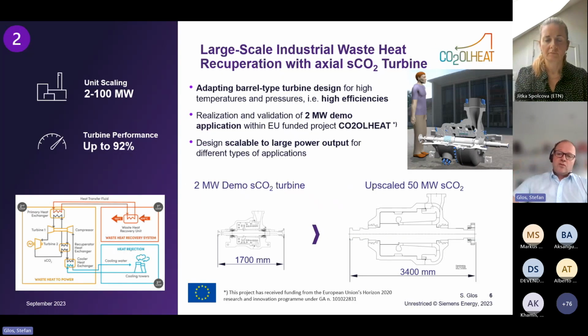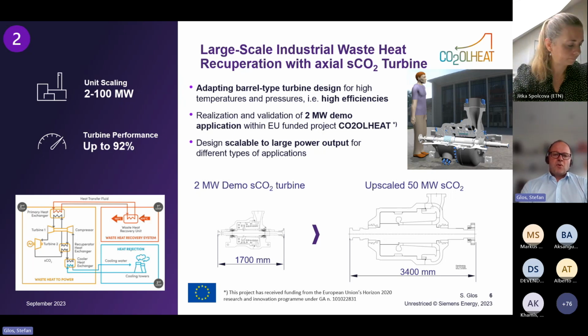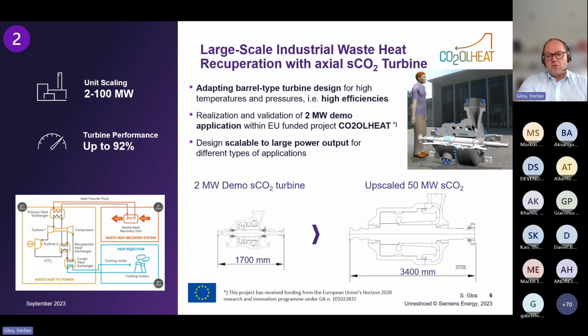So, as already mentioned, within the European-funded CO2OLHEAT project, we have designed a high-pressure barrel-type turbine for sCO2. The goal is the realization and the validation of this demo plant. Unfortunately, this project is still on hold, but we are working on further progress. But we always had in mind to have a design which is then scalable to larger power output, and we did that exercise, which is roughly shown here on the lower end of this slide. So for 2 megawatt, we get a rotor length of roughly 1.7 meters, and if we scale that up to 50 megawatt, for instance, we have only a shaft length of 3.4 meters.